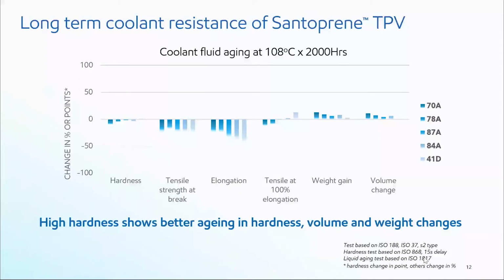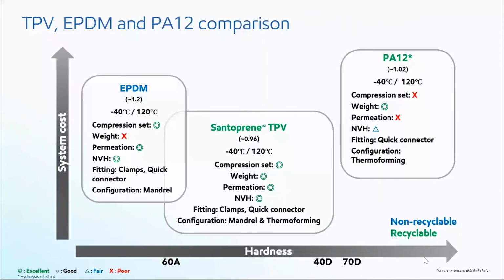So this is a very interesting slide here. This puts a comparison of Santoprene TPV versus other materials which are used to make hoses, like EPDM rubber or polyamide 12, which is seen in the industry. So clearly we can see that the total system cost of making an EV coolant hose with Santoprene is much cheaper than an EPDM and a PA12. And coming to the hardness range, Santoprene has a very broad hardness range from 60 Shore A to 40 Shore D. That means Santoprene can be used to make hoses which are softer as well as harder.